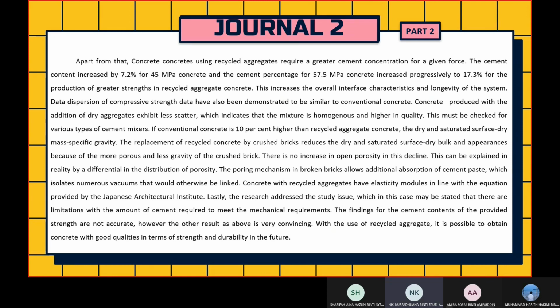If conventional concrete is 10% higher than recycled aggregate concrete, the dry and saturated surface dry mass specific gravity. The replacement of recycled concrete by crushed brick reduced the dry and saturated surface dry bulk and appearance because of the more porous, lower specific gravity of the crushed bricks. There is no increase in open porosity in this decline. This can be explained in reality by a differential in the distribution of porosity. The poring mechanism in broken bricks allows additional absorption of cement paste, which isolate numerous vacuums that will otherwise be linked. Concrete with recycled aggregate have elasticity modulus in line with the equation provided by the Japanese Architectural Institute.